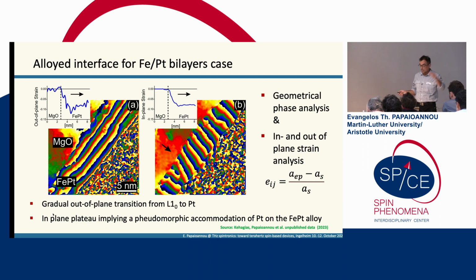So we use as a reference the substrate, and using the substrate as a reference, we see that out of plane we have the strain that corresponds to iron, then gradually goes to the alloy here, and then goes back to platinum. And then the very interesting thing is that the in-plane strain seems to be just one. And this indicates that we have a kind of a pseudomorphic accommodation of platinum in the alloy. So in other words, I would say it's a kind of a continuous alloy. So not an alloy, a kind of a special structure of continuous alloy.